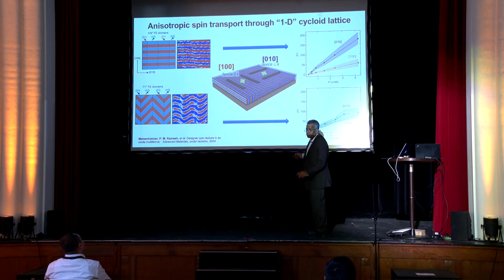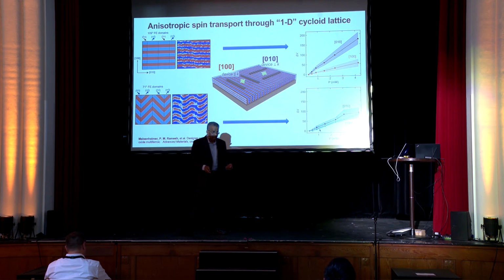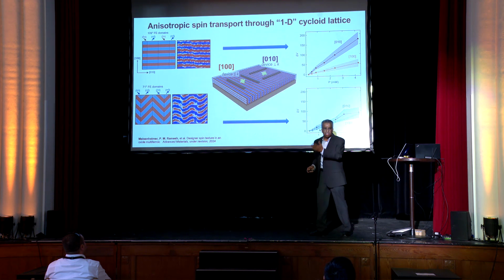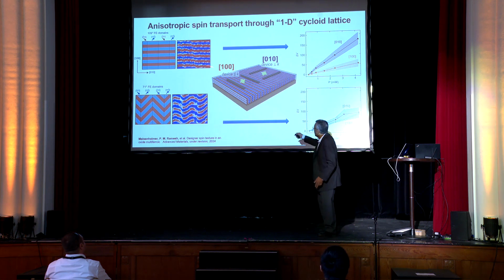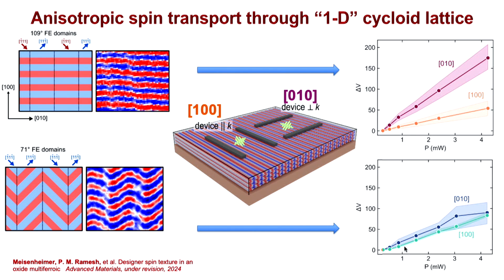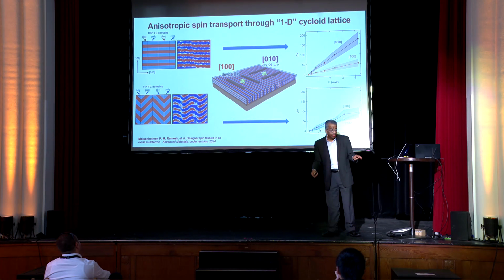If you measure spin transport, I'm going to get into the details of the spin transport in just a second. If you do spin transport through them simply by launching spins through the system, in this case, you would have magnons in the multiferroic. There is a very large anisotropy parallel and perpendicular to these cycloids. So you can now start to probe transport of spins through these tubes of cycloids in the system. If I do the same experiment for the zigzag or the chevron pattern on dysprosium scandate, you see no anisotropy. So you can now start to use pathways like this to create a band gap, for example, in the magnon spectrum of these systems and start to probe them. You can manipulate them with an electric field and so on.